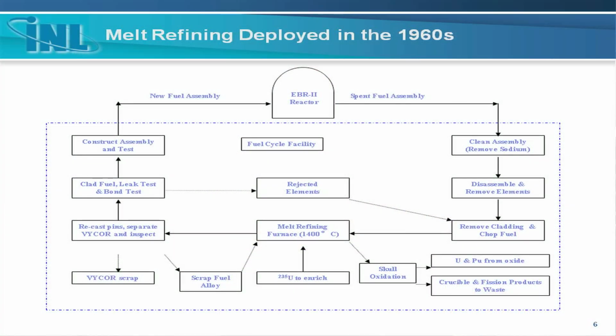In general, what you do is you chop the fuel, remove the cladding, take the fuel material, and place it into a crucible, which in this case was made out of zirconium or zirconium oxide. You take the fuel in it and heat it up to 1400 degrees C. In doing that, the gaseous fission products are released, and most of the active fission products, things like cesium, strontium, the rare earths, tend to react with the crucible itself. They would stay behind in the crucible as a skull on that zirconia crucible, and you could then pour out the metal fuel and use it to refabricate fuel.